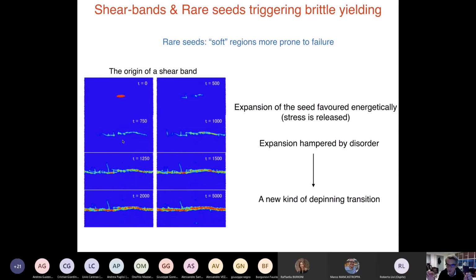But this can be understood, and I don't really have time to go into the detail, but you can ask me if you want, using the anisotropic property of the elastic kernel. You can understand that the better way to have a seed that propagates is this: if I relax here, then this relaxation, this deformation, this failure, will induce a failure here at the boundary, which will induce a failure at the boundary, and so on and so forth. It is really this geometry with a shear band. And so what we have to study to understand this problem now is a kind of depinning transition.